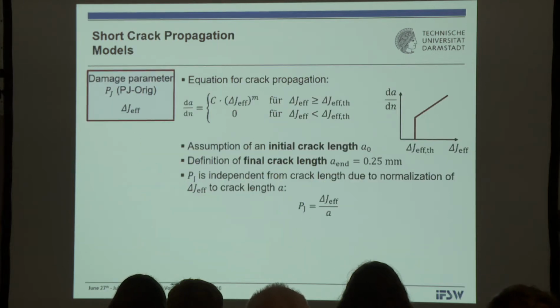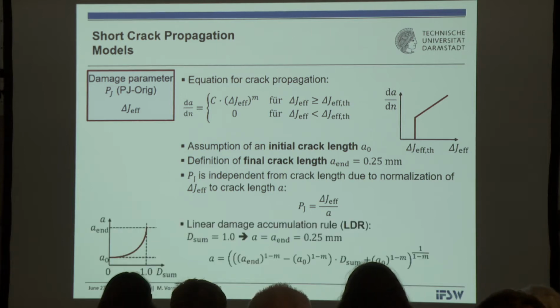So as I said, the crack driving force is the J integral, with a power law similar to the Paris law, now formulated in ΔJ. Keep in mind that the damage parameter is simply ΔJ divided by a. The crack is assumed to start at an initial crack length, and you have to define the final crack length, and then you can integrate that power law here. And if you integrate that power law and normalize the crack growth curves by the end value, then you again end up with an affine crack growth curve or damage growth curve, which means that in this case you can apply linear damage accumulation, now expressed in terms of constant amplitude life curves in terms of this P_J parameter.